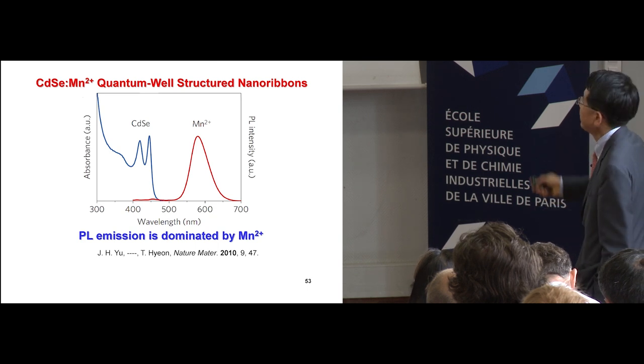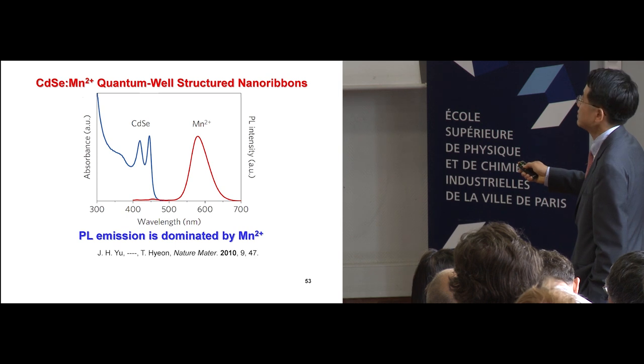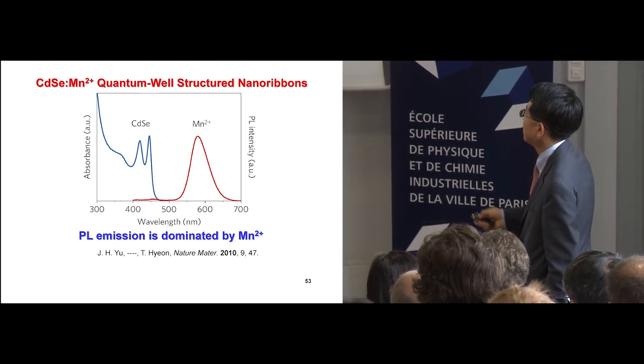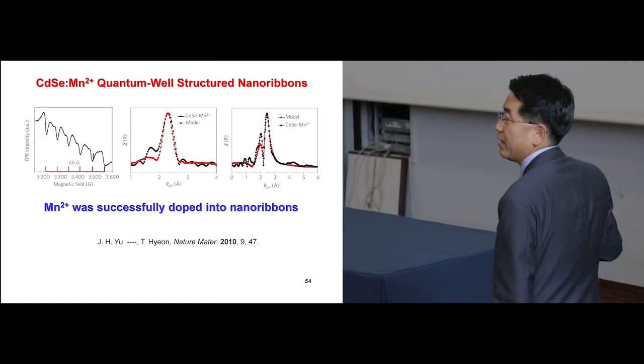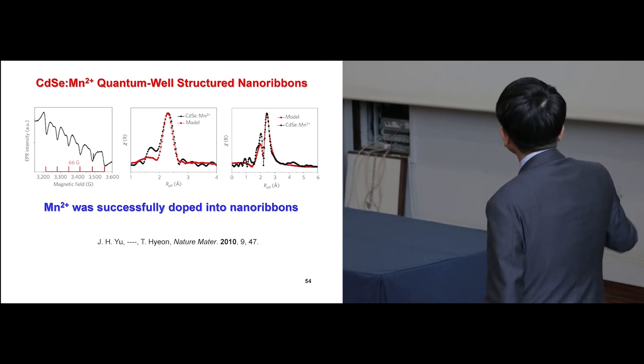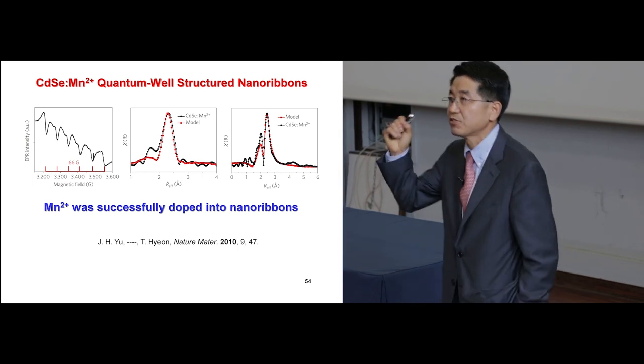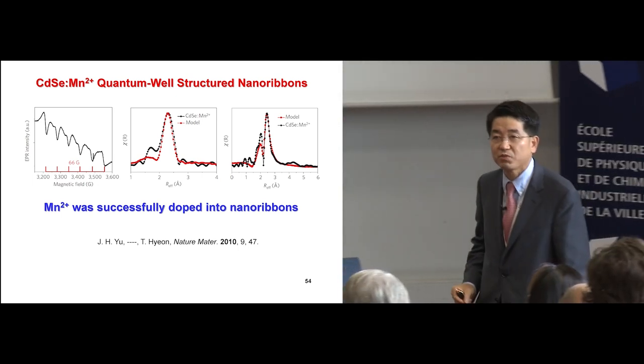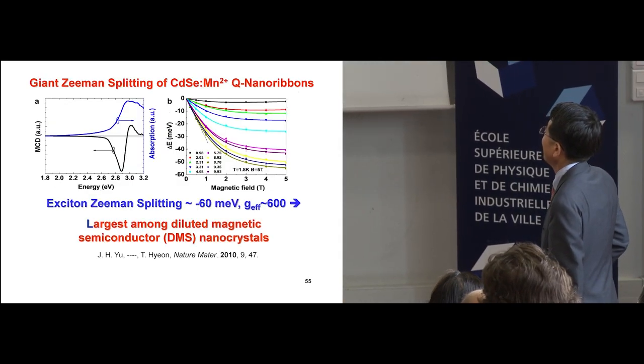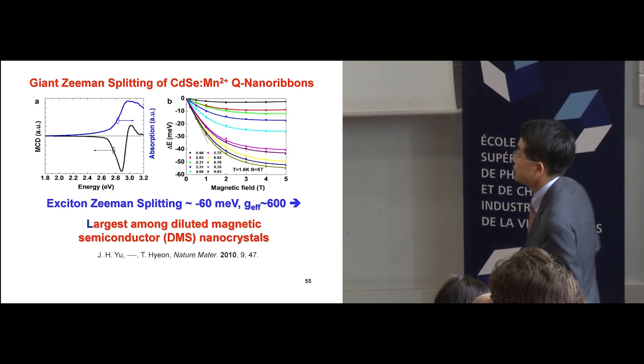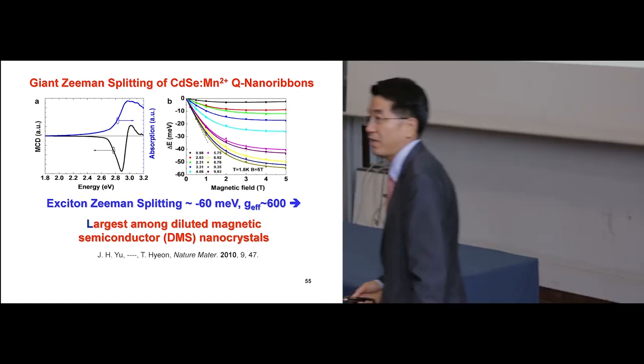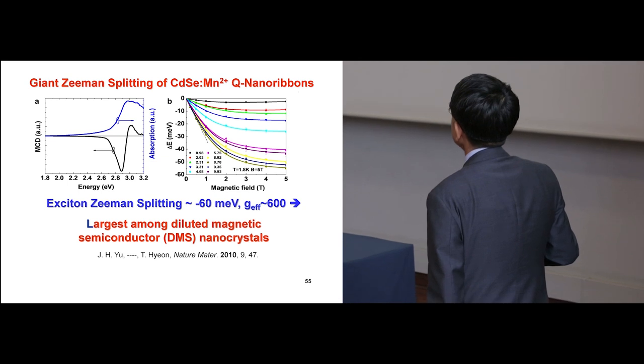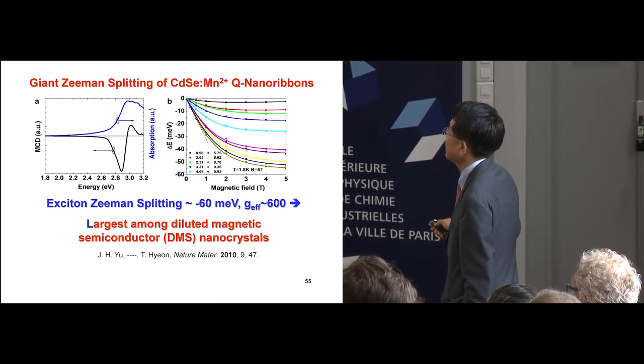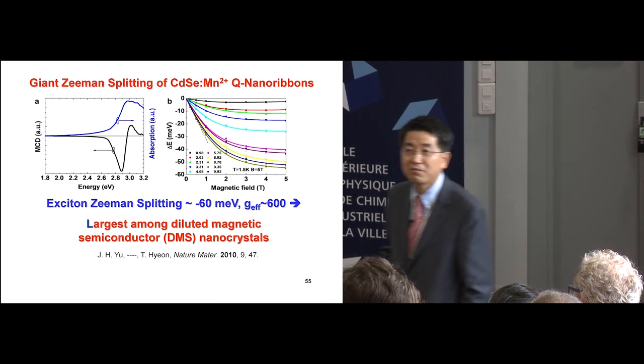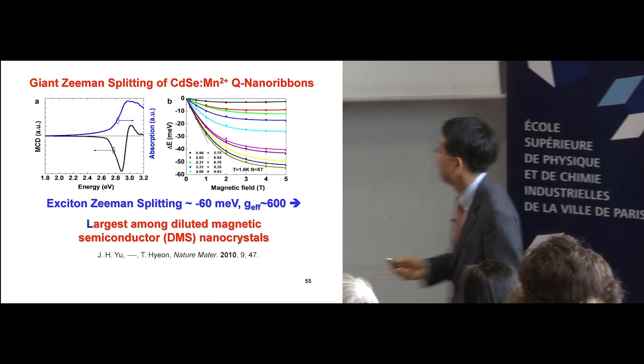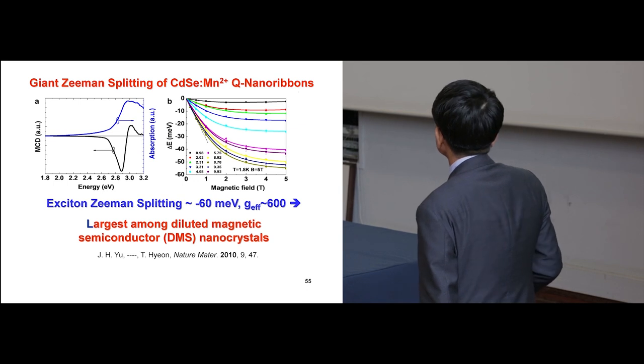That's very challenging, but this was possible. First, the PL gives manganese photoluminescence, clearly around 580 nm. Then we did the EPR, the signature for Mn2+ doping, and the XPS clearly shows that Mn2+ is successfully doped inside this very thin CdSe nanoribbon structure. Then, in collaboration with Jacek Furdyna's group at the University of Notre Dame, he did a magnetic measurement. We could see a very high g factor of 600. This is still a record for DMS, dilute magnetic semiconductor nanostructures. Very high effective g factor, and the excitonic Zeeman splitting is also quite good.